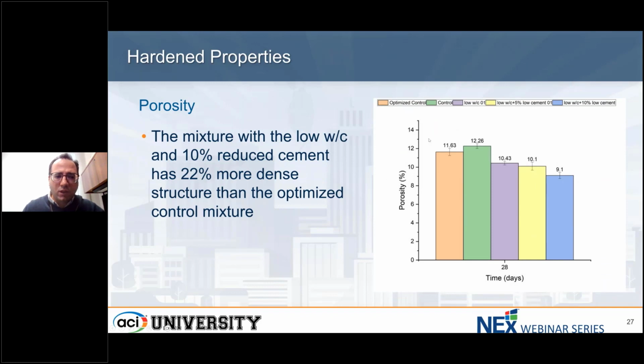We looked at the porosity of the system. We basically oven dried the system, vacuum saturated it, and submerged it in water to get the weights, and then measured the porosity based on ASTM. And these are the results. So we see the porosity for the control, number 57, is 12.3 percent, and it reduces to 9% for the low cement, low water cement ratio system. That's almost 22% lower porosity, or denser microstructure, for our optimized sustainable system. So you see, it's very correlated with what we discussed in the compressive and flexural strength experiments, the impact of higher packing density and improved microstructure.